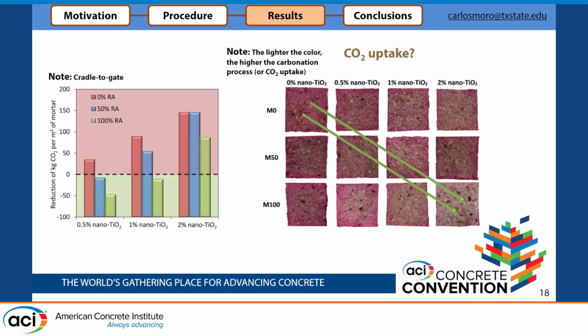Okay? We still have a chance that if we can uptake this percentage of CO2 during its service life more than the reference sample, our mortars are going to be even more sustainable, are going to decrease the overall impact that these materials have. And not only that, but in the 0.5% of nanoparticles with 100% of recycled aggregate that we already had a negative value compared to the reference sample, we can improve even further.